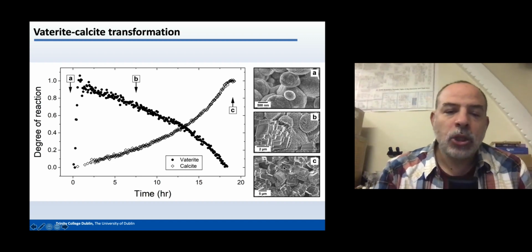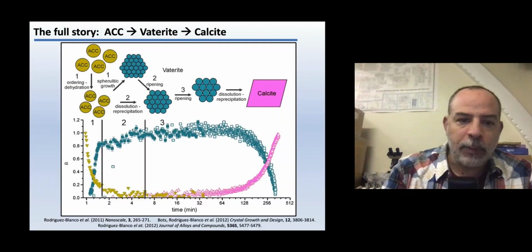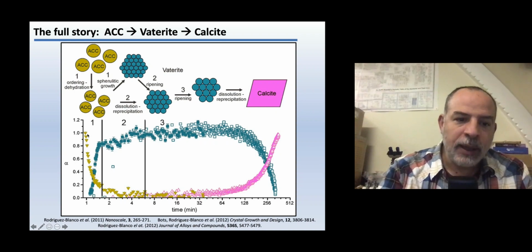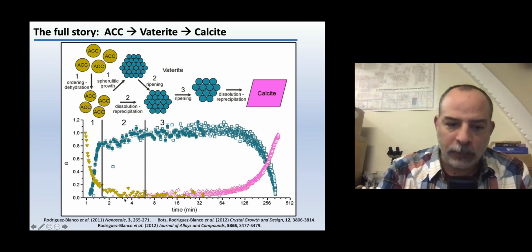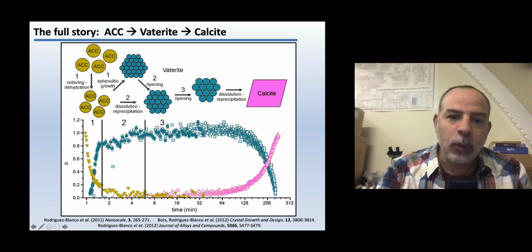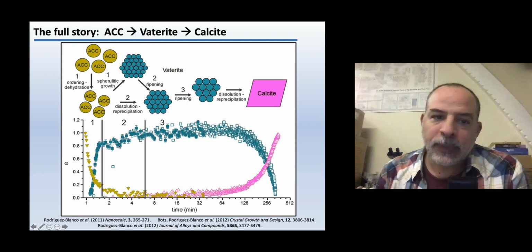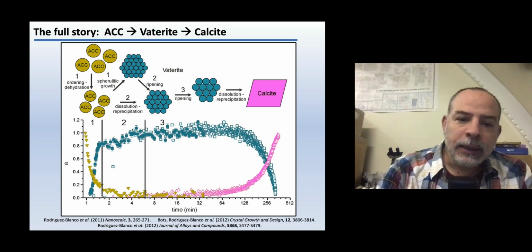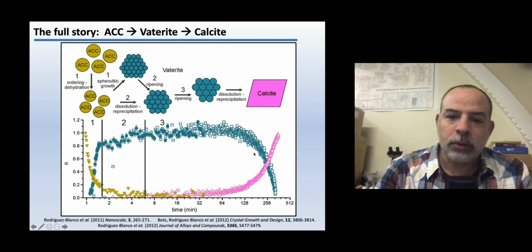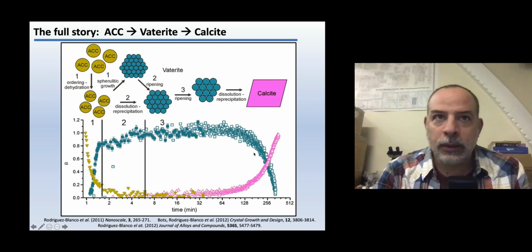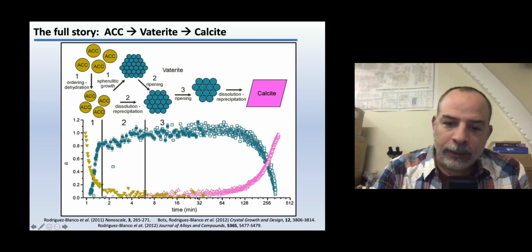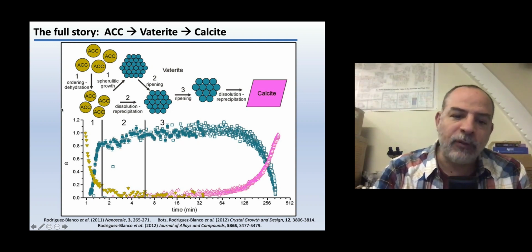So if you put all this together, you could have a picture like this, in which you have a quick decay of the amorphous calcium carbonate, extremely quick growth of vaterite via spherulitic growth, and then a slow decay, dissolution of vaterite, and crystallization of calcite. This is the full picture.